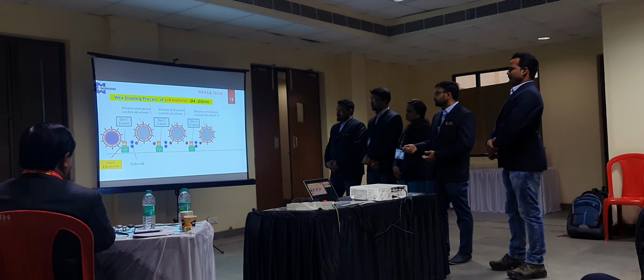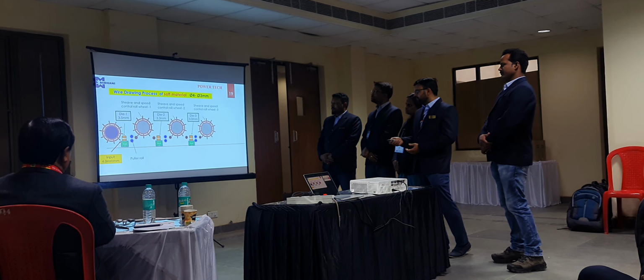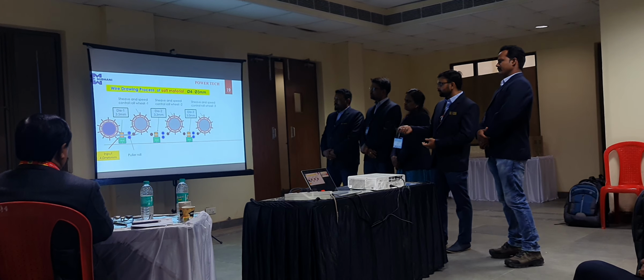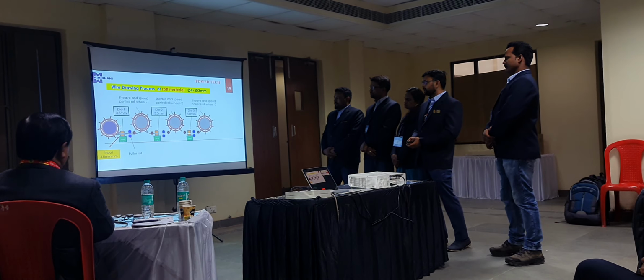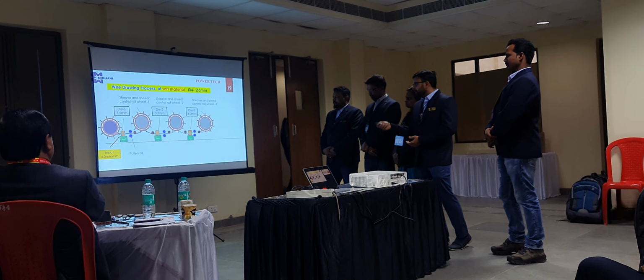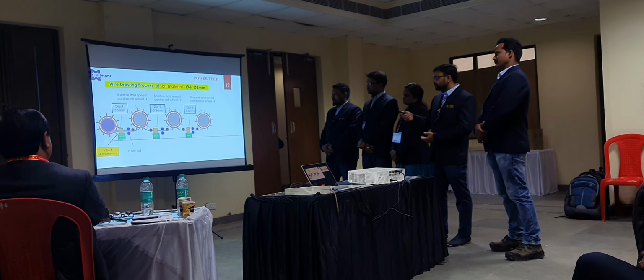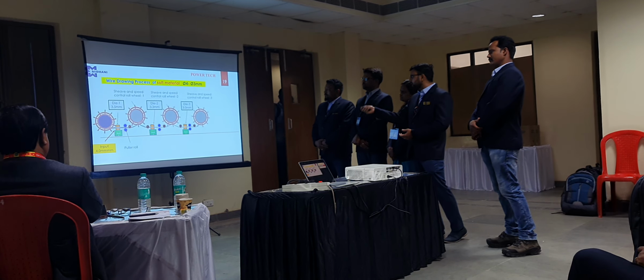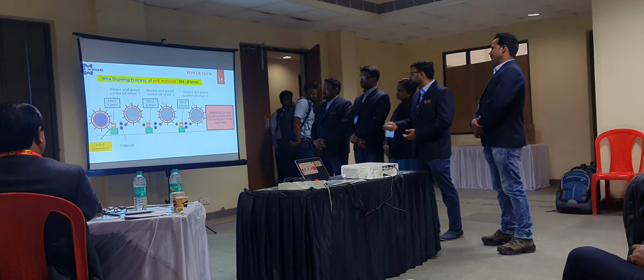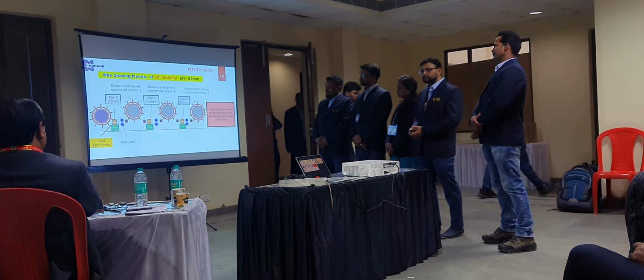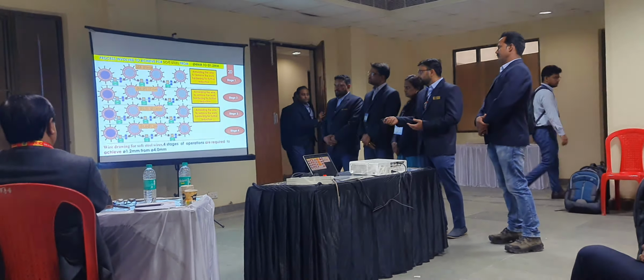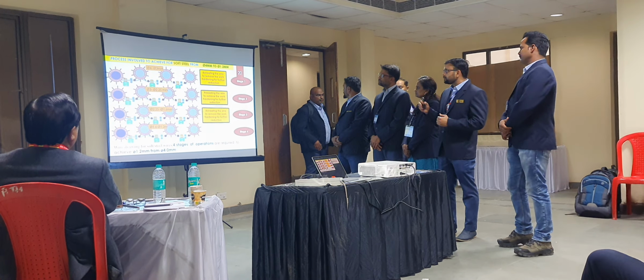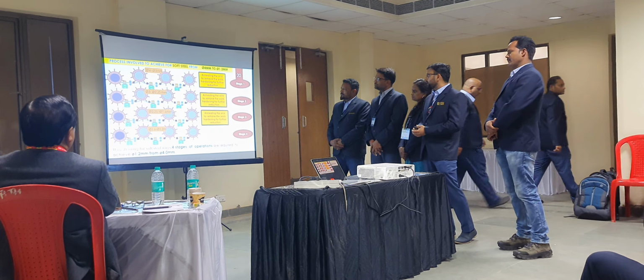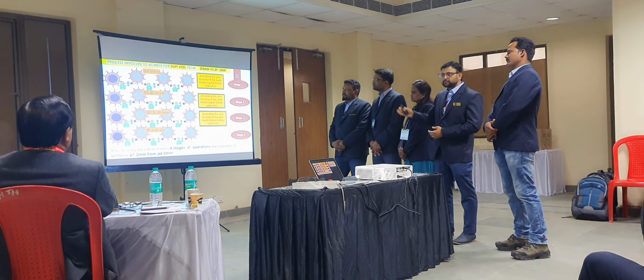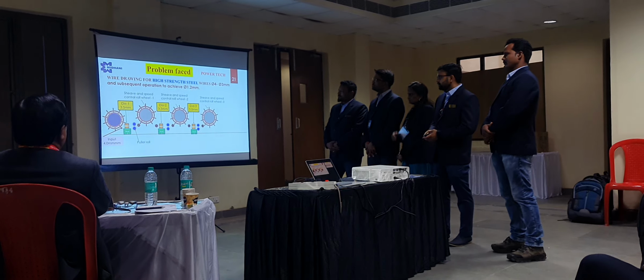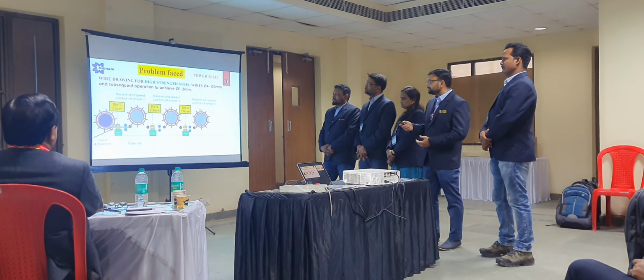This is the animation video where we show how the wire drawing process happens for soft material from 4 dia to 3 dia. We have 3 sets of dies: 3.5, 3.3, 3. With each reduction, the input size of 4 is reduced to the next size and ultimately it reaches 3 mm. At this stage, we have to send the wire for annealing to remove the work hardening for further reduction. So the process for real production of soft steel from 4 to 1.2 dia requires 4 stages with 3 intermediate annealing cycles.